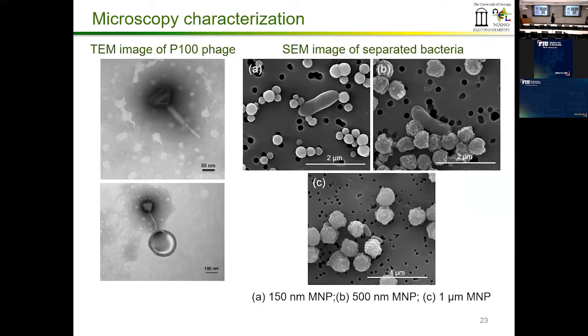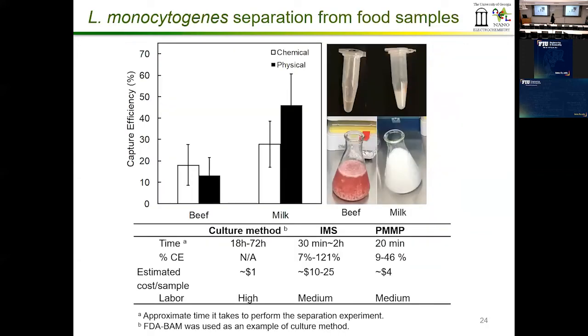Some SEM images showing that the bacteria is attached to the magnetic particles, 3 different sizes of magnetic particles, and here is the virus. This is actually a TEM image, and this shows only one virus, but you can also see there is tons of other things in the background that's not really captured here, that is on the surface. So far everything was done in liquid buffer samples.